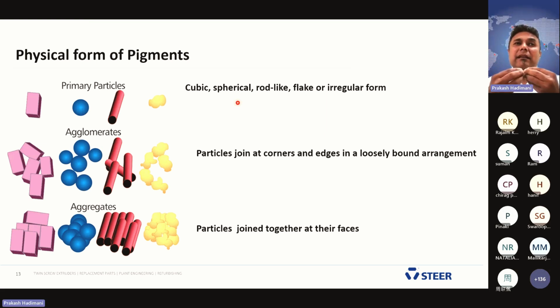Again, in the particle size of the pigment history, we categorize agglomerated particles, we call them agglomerates, and aggregates. These are two phenomena. Agglomerates tend to form when this particle and this particle join in the corner, not attached on the surface. Agglomerated particles attach at the corner or at the angle. Only in the angle are they attached, and it's easy to disperse.